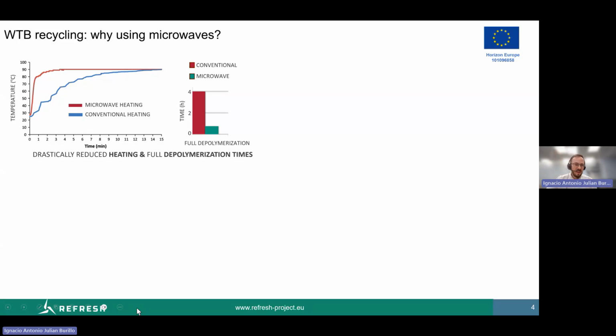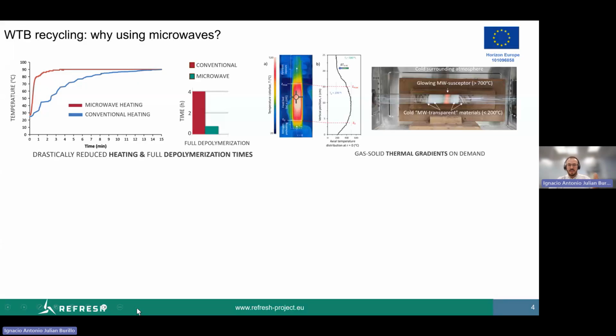As you can see here on the top left, the temperature rises much faster to reach a constant temperature for pyrolysis compared to conventional heating, but also the full depolymerization times for the resins contained in the composites are drastically decreased by using microwave heating. As you can see, the process is more than 5 times faster. And the reason is that we can heat selectively the material that we want to process.